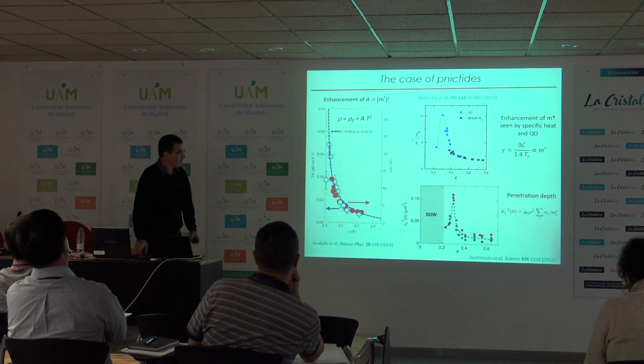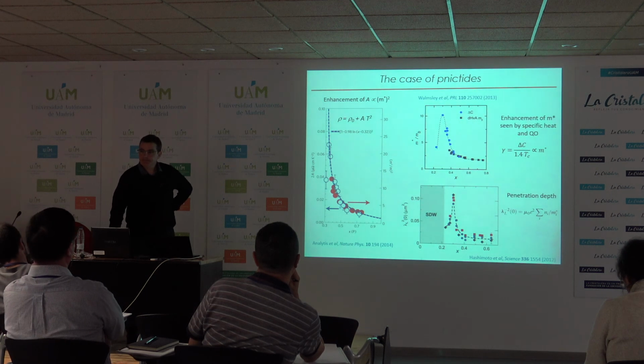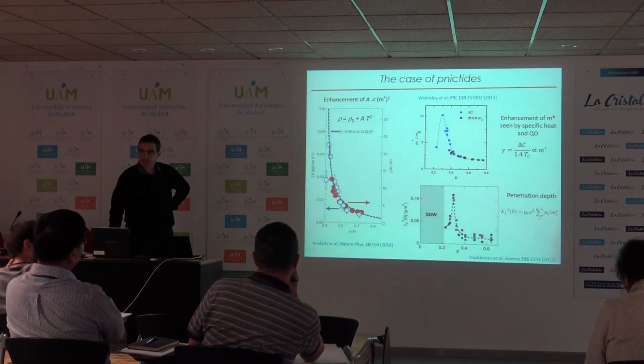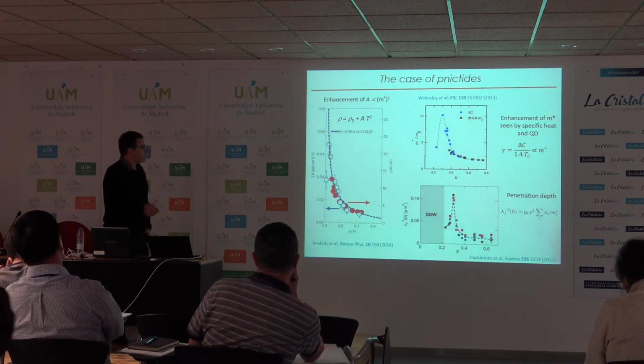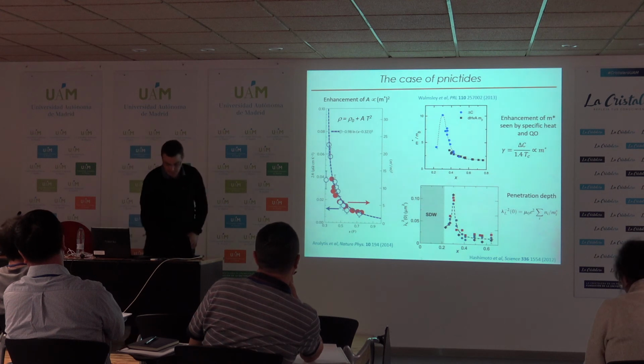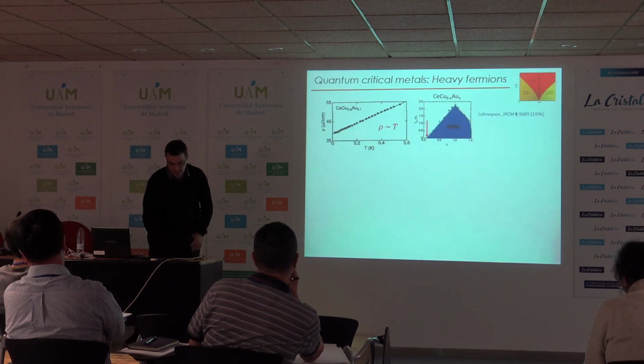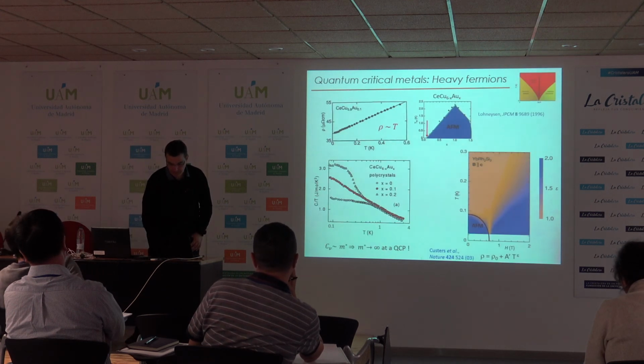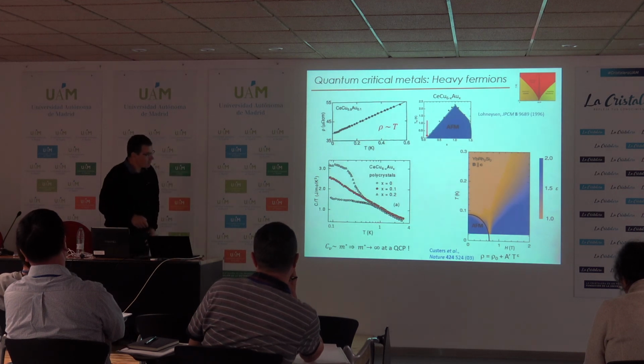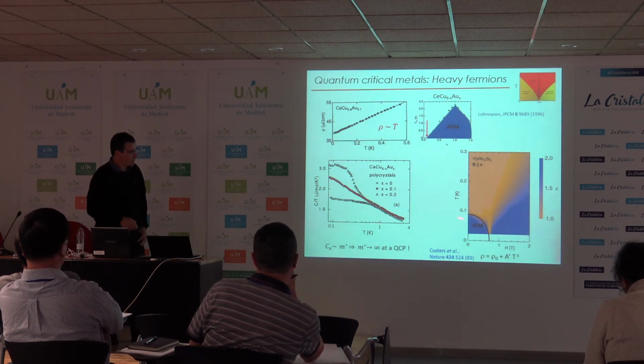And here the resistivity is not linear in T. It is linear in T only at the critical point. So you see, in a conventional system, you expect to have a fan like this. The linear resistivity extends down to T equals 0 only at the quantum critical point.